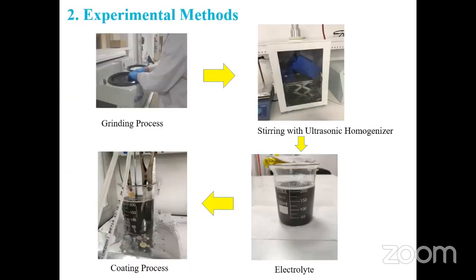Experimental methods. In the study, copper substrates were used, and these copper substrates were ground with 240, 400, and 600 silicon carbide grinding paper by using a metal grinding device respectively. After grinding, they were cleaned with acetone and then degreased with pure ethanol solution for 1 minute and cleaned with pure water before coating. Then, the prepared bath solution was treated by ultrasonic homogenizer for 1 hour to ensure that the nanoparticles did not precipitate in the bath and were homogeneously dispersed. And finally, the coating process was carried out.